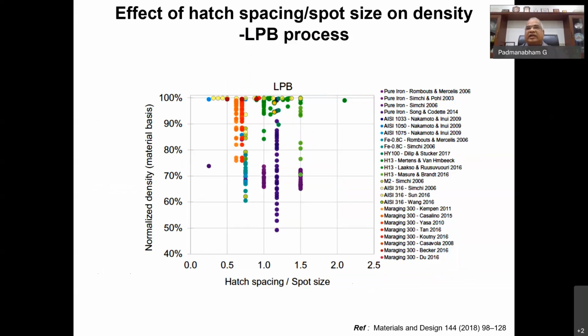For example, the next parameter: when you scan, you have the laser beam scanning one line, and after that, the next line is overlapping the first line. That depends on the size of the spot of your laser beam. In such a case, you can see here the effect of hatch spacing. The line to line distance is called the hatch spacing, and you have the spot size. Even the ratio of the hatch spacing to spot size can decide the kind of density that you can arrive at. So you can see the window, the variation that can happen depending on the hatch spacing and spot size.